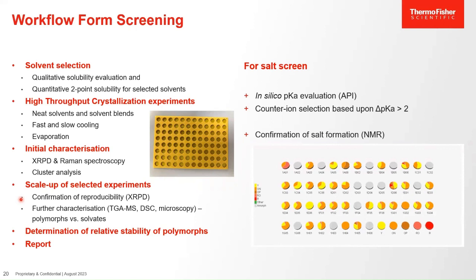Polymorphism is notorious for being scale dependent. The smaller your crystallization system is, the more likely you are to find more polymorphs. Now, in actual fact, in most cases, we're not interested in many polymorphs. We're interested in process-relevant polymorphs, and this scale-up is the first test: whether the polymorphs we found in the small-scale screen are actually relevant, whether they can be reproduced. And this is a simple matter of subjecting the powders to X-ray powder diffraction, making sure they're the same as in the first experiments.